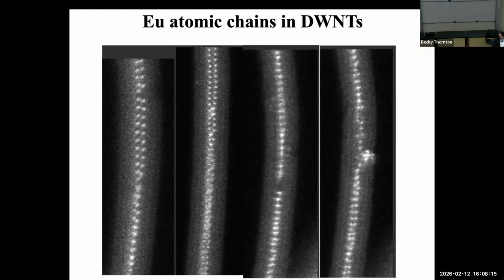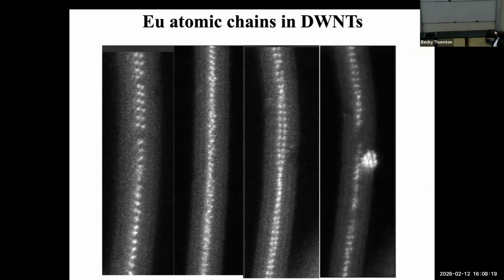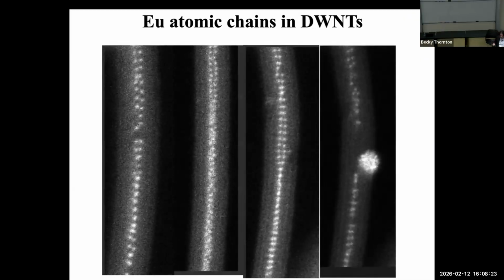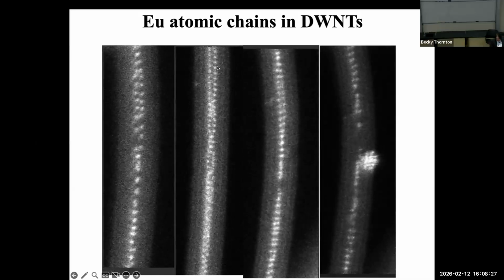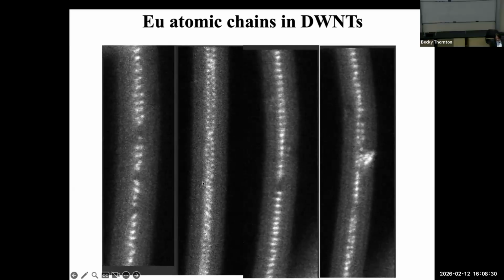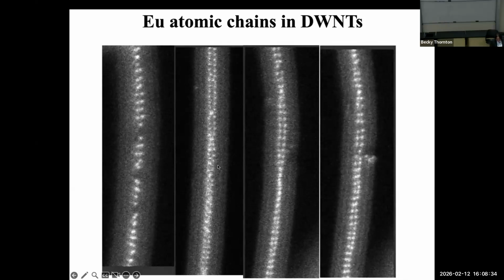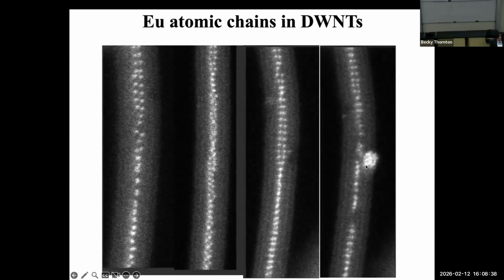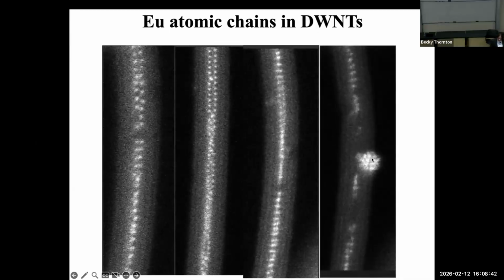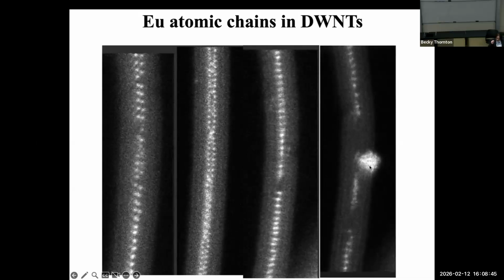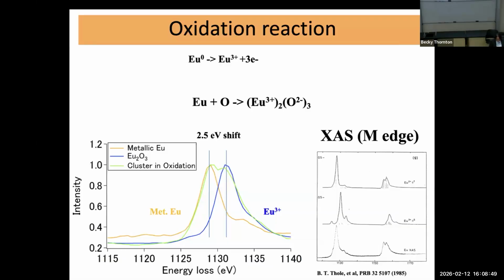Okay, so this is an example of chemical reactions. We put some europium atoms in the carbon nanotubes, and they are moving around. But sometimes it's getting oxidized. In this case it's going out, so this becomes europium oxide. We want to try to track this oxidation reaction by spectroscopy. If you have europium metal, the EELS peaks will appear here, but when it becomes oxide, you have a 2.5 eV shift. So we could track the chemical reactions happening inside the nanotubes.